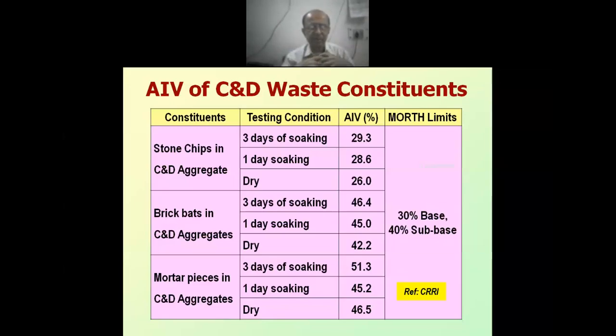So we did the wet AIV as well as the dry AIV test, and also 1 day soaking, for different components like stone chips, brick bats and mortar pieces separately, and you can see these are the values. Stone chips are easily satisfying. Brick pads and mortar pieces are a little bit difficult. It's a little bit more than 40% for the sub-base, but this will be intermixed with the other material in C&D waste. So when all these three are intermixed, the overall percentage comes down to 30.